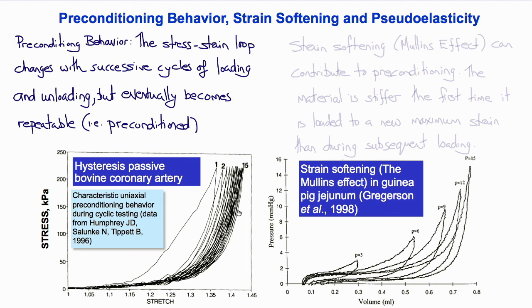This is important in experimental testing of soft tissues, and it is normal protocol to perform repeated cycling of loading and unloading to ensure that the tissue is preconditioned before reporting stress-strain behavior. The reasoning is in part that tissues in vivo are more likely to be in their preconditioned, naturally, regularly loaded state than in the state they are when freshly excised.